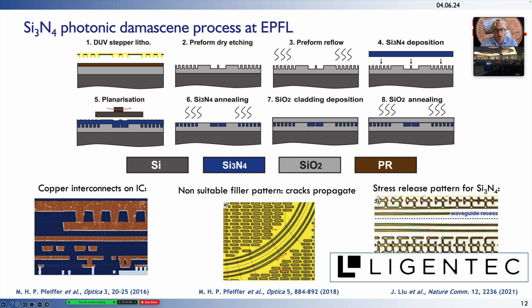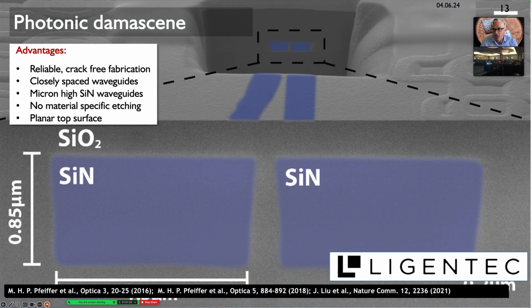So this technique actually allowed us to make tightly confining integrated photonic waveguides with low loss of silicon nitride. This technique that we're using here is very similar to the copper damascene process. That's why we call it a photonic damascene process. It's commercialized with the company Ligentec that I co-founded some 8 years ago, and that provides foundry access to this material. This technique allows us to create crack-free silicon nitride waveguides with exceptionally low loss.